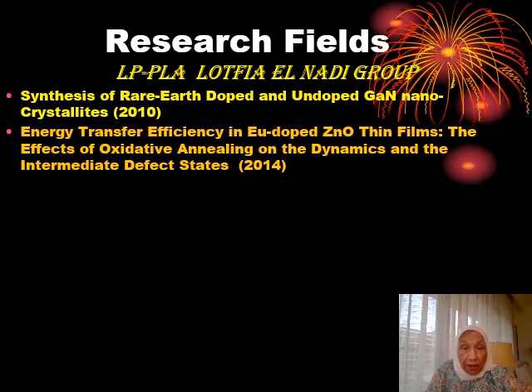And we did other work at Georgia Tech Institute together with Professor Mostafa El-Sayed and Samah. That was on energy transfer efficiency in europium doped zinc oxide thin films. And this has been published in Applied Materials and Interfaces, which is published by the American Chemical Society.